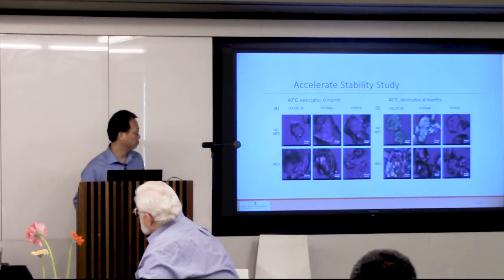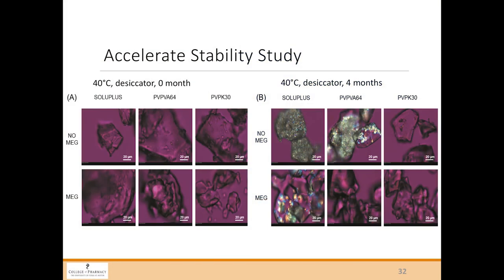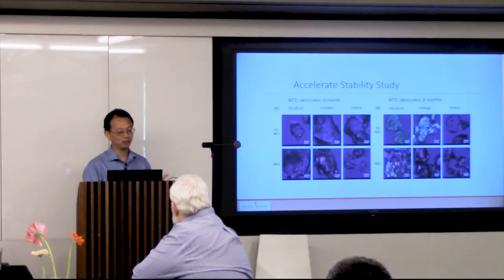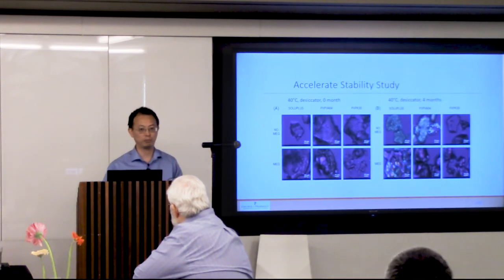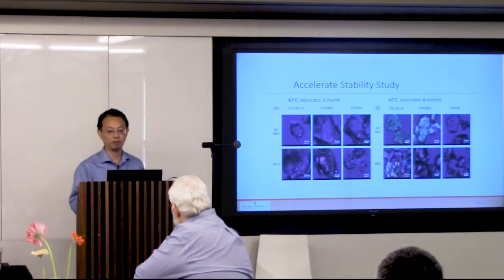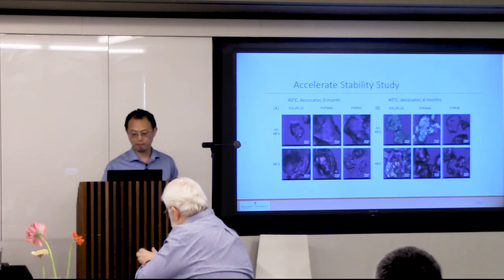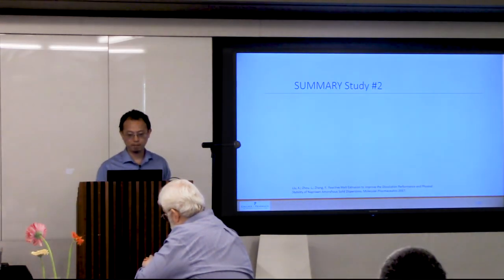And we put them on stability. So this is the initial time point. Without MEG, after 4 months storage, they crystallize because naproxen is a very fast crystallizer. In the case of MEG, the best ones we find are PVP and copolymer. We have observed crystallization in Soluplus. I think it has a lot to do with Soluplus having a very low crystallization temperature. In the case of copolymer and PVP polymer, both are actually stable.